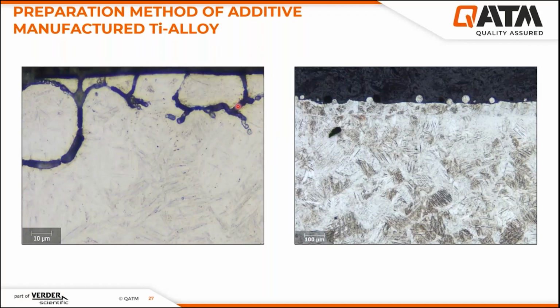Here, the lack of fusion on the grain boundaries can be seen on the left-hand side very clearly, and also we can see the edge of the sample without any rounding and without any gap between the material and mounting material on the right-hand side.